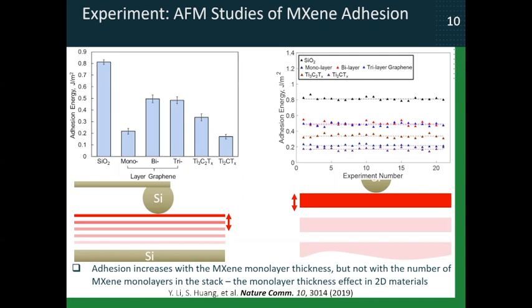So we can fabricate graphene on silicon and then put MXene on top of graphene and then put graphene again, which is critical if you envision applications of MXenes in electronics, because this is how we fabricate all components of electronics. It's just stacking of different layers, right? And it's very important that the adhesion strength is similar for graphene and MXene, because it tells you that you can seamlessly integrate all these materials, graphene, other MXenes, without developing mechanical stresses between them due to differences in adhesion.